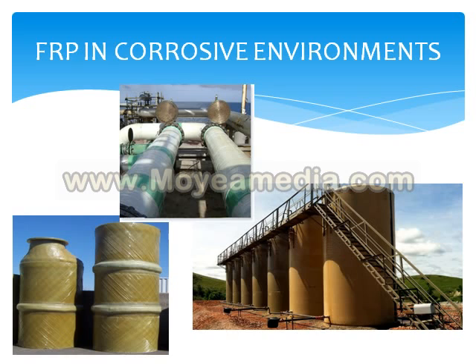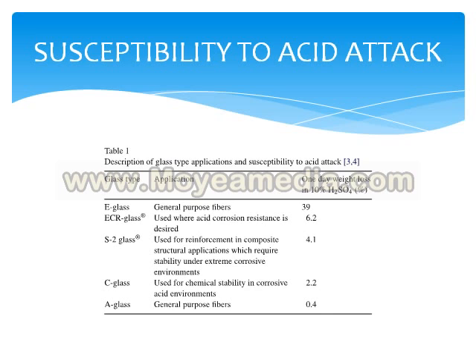The structural integrity of these fiberglass components is usually dependent on the integrity of a corrosion-resistant barrier, which is constructed of an outer layer, 0.1 to 1/4 inches thick of 95% resin and 5% corrosion-resistant fiberglass, followed by an intermediate layer of acid-resistant chopped fiberglass with 75% resin, and then those are surrounding the inner part, which will be E-glass.